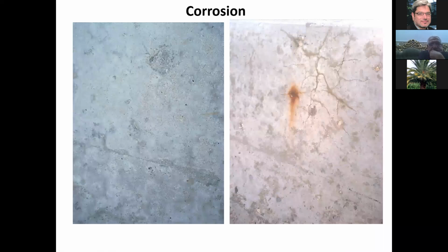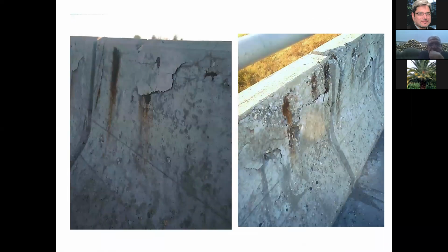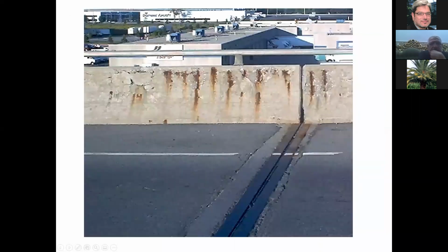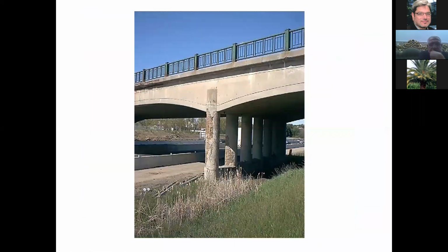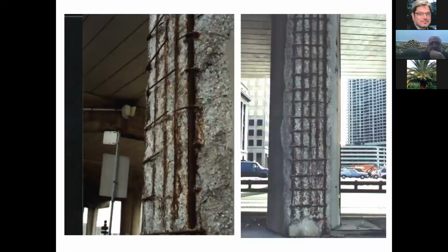Corrosion causes fracture of the concrete surface, because the reinforcement inside the concrete, when it corrodes, expands in volume. So it starts to push the concrete cover, and you can see the color of corrosion seeping through these cracks. There are many such examples. This one is from Canada, to show how much damage the steel corrosion has caused.